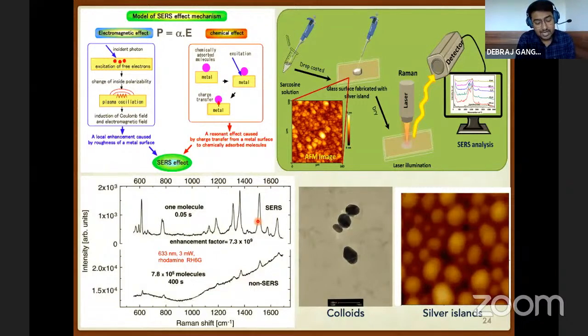So when this ANALYTE is adsorbed on a silver or gold surface, there can be two effects. One is the electromagnetic effect, and another is the chemical effect. Now, the intensity of Raman spectra is governed by this formula, where alpha is the polarizability and E is the electric field. In case of the electromagnetic effect, due to the plasmon oscillations in the vicinity of the metal surface, there can be an enhancement in the electric field, the localized electromagnetic field. And this localized electromagnetic field may further enhance the Raman signal coming from that ANALYTE.